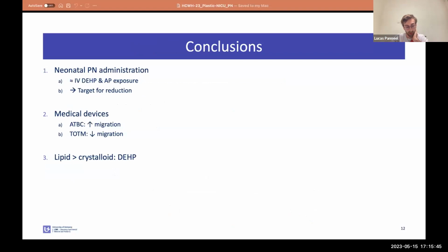To conclude, our data indicate that premature neonates requiring parenteral nutrition are still intravenously exposed to DEHP, albeit lower than in previous studies, and to a range of alternative plasticizers, making a target for reduction, as shown in the tables by Pauline. And ATBC seems to leach significantly from the devices, while TOTM might be present, but leaching in very, very low amounts. Probably being a good alternative plasticizer.